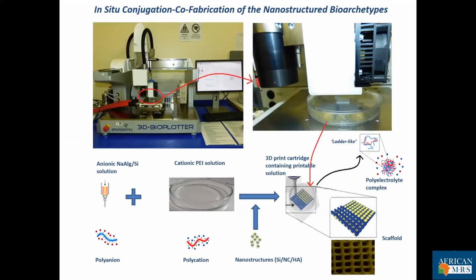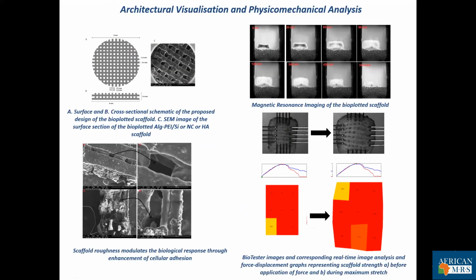So the single step approach employed here was by combining your anionic and cationic hydrogel together with your nanostructures as a single bioink, which was then 3D printed, and then forming that polyelectrolyte complex by the interaction of course, your anionic sodium alginate and your cationic PEI. SEM visualization shows basically that you have a structure that replicates the required surface roughness in an extracellular matrix environment for promoting your cellular adhesion.